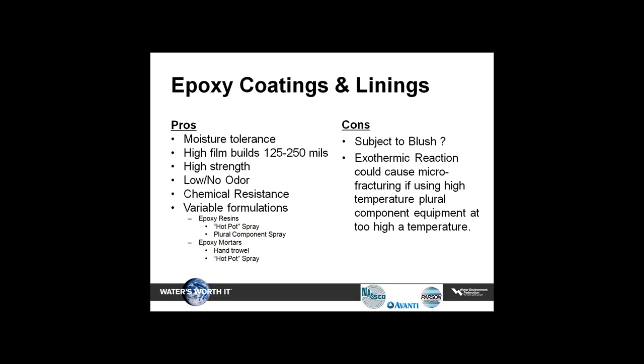Some of the pros of these epoxies are they are moisture tolerant. They go to surface saturated conditions. A very high film build, 125 to 250 mils or up to 1/4 of an inch. Very high strength, very low or no odor. They're generally 100% solids. They are very chemical resistant. They come in variable formulations, and the resins can be hot pots or applied very quickly through standard equipment or through plural component spray. These epoxies can also be made into mortars and hand troweled into place.